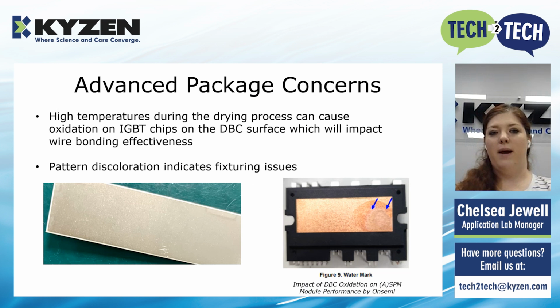Also looking at advanced packaging, mostly what we've talked about thus far has been PCB, but when you get into advanced packaging, the quality of bond and the complication level there is so much higher. So when you look at these surfaces, high temperatures during a drying process can definitely cause oxidation on the surface, and that's going to impact your wire bonding.